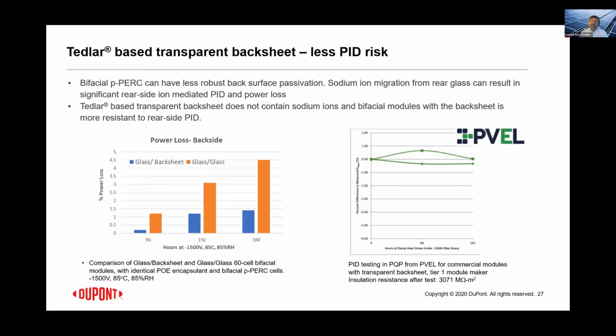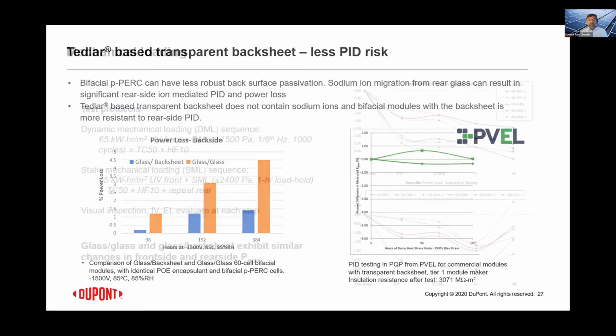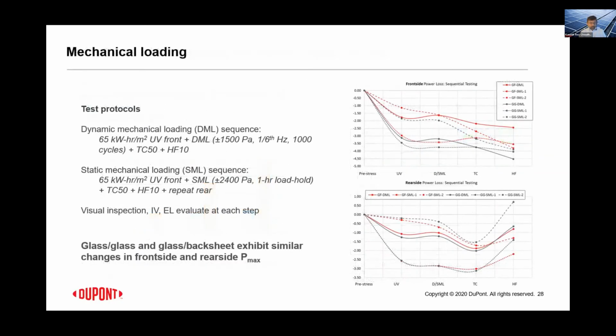Another example from a module that was taken through PID testing at PVEL, and this is actually for 96, so actually 192 hours. And we see hardly any loss in power in this particular case with a transparent Tedlar-based backsheet. Again, gives us the confidence that there will be not much PID risk in these module prototypes. I also heard mechanical loading, and I'm pretty sure people will have questions around this as well. So we did check. This is, by the way, a work under progress.